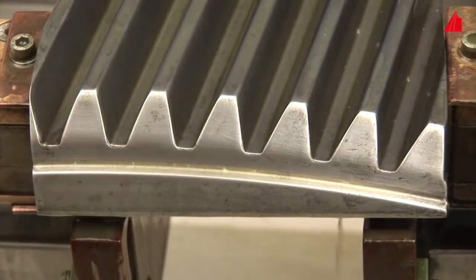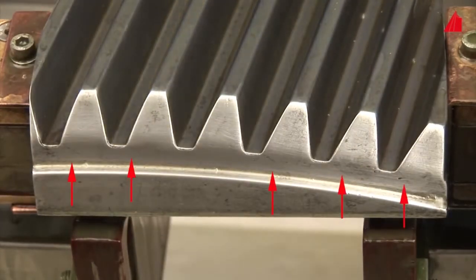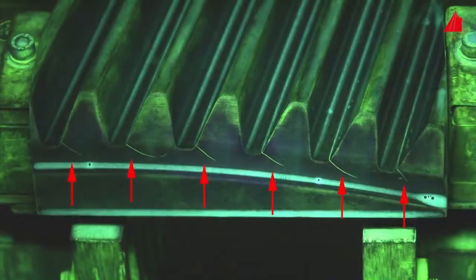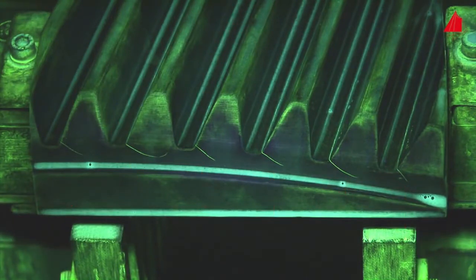Already in daylight, there are indications of cracks, and again, they are best visible under ultraviolet light while darkening the daylight. The visible cracks are so-called fatigue cracks. They have been generated during the operation of the gear drive due to a mismatch of the gear wheels.